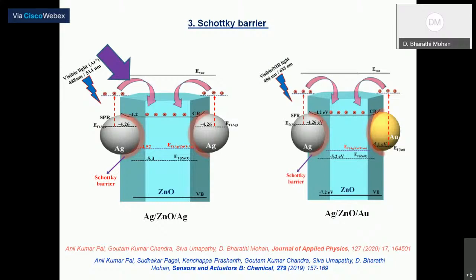The enhancement of the Raman scattering can be explained through Schottky barrier formation. When you deposit silver or gold or platinum on the surface of zinc oxide nanorods, there is formation of a Schottky barrier between the metal and semiconductor, because zinc oxide is a semiconducting material and silver is a metal. So when you make a contact, there is Schottky barrier formation. Because of the Schottky barrier formation, there is a charge transfer from the metal to the semiconductor.